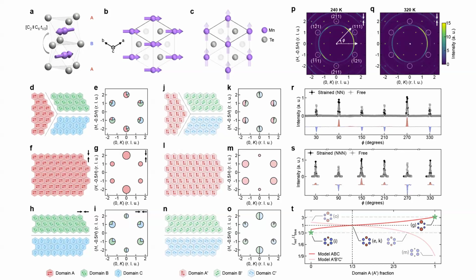It's 3 orders of magnitude smaller than in the case of manganese tin. So this is one particular case. Wei Liang, who's sitting there, has done a separate system, hexagonal iron sulfur, which has a larger magnetostriction, 1 order of magnitude larger than manganese telluride. So manganese telluride seems to be the only system with a tiny amount of magnetoelastic coupling, really suggesting that the effect we're seeing is purely electronic.